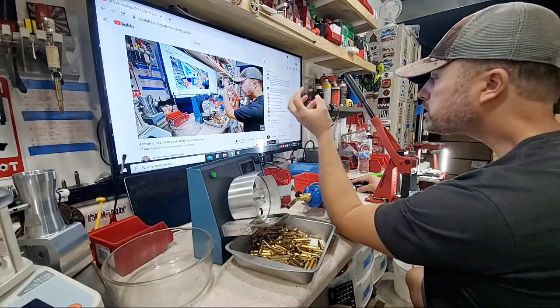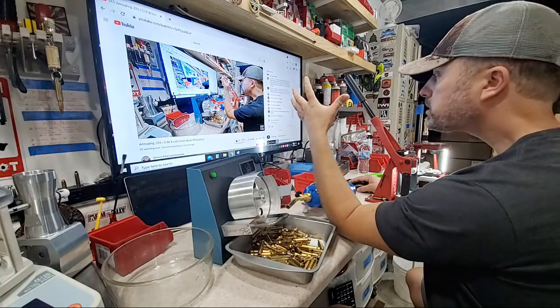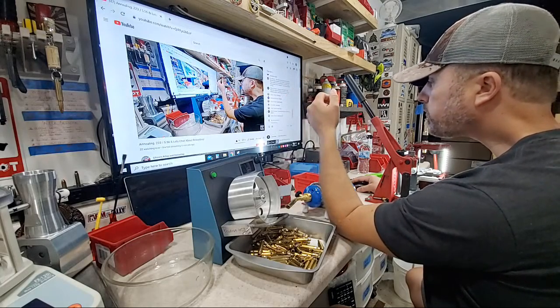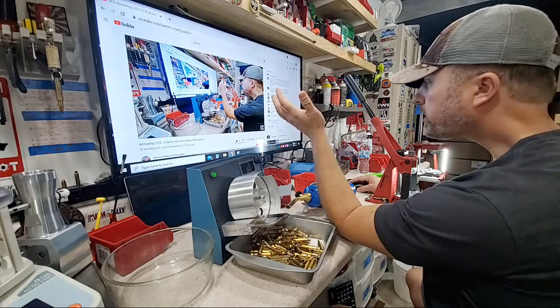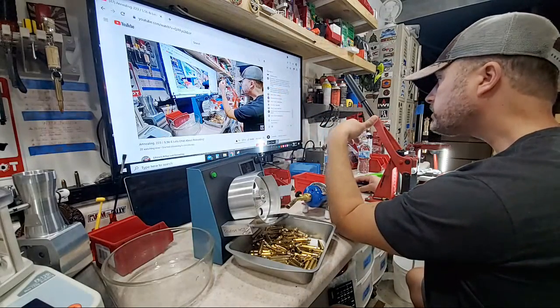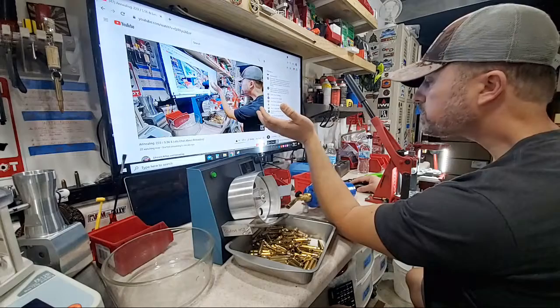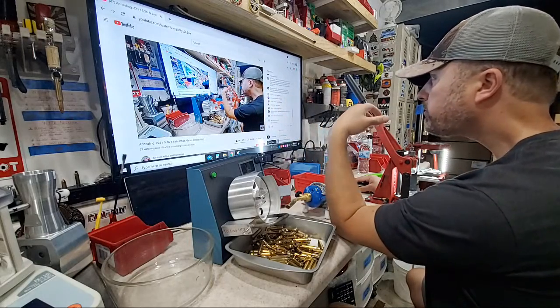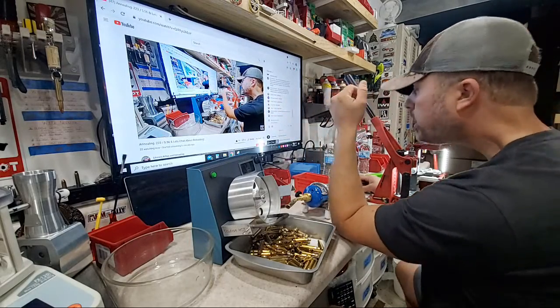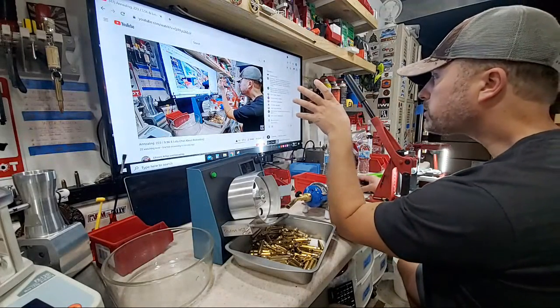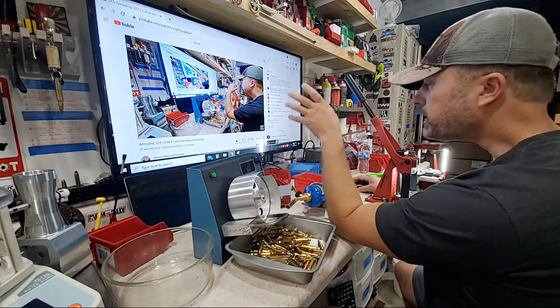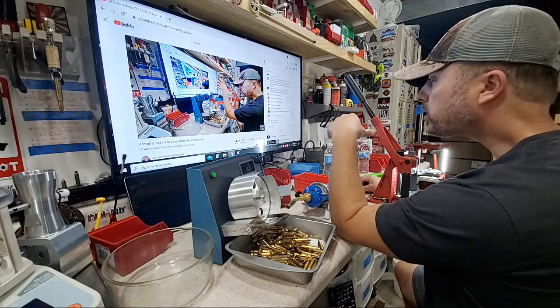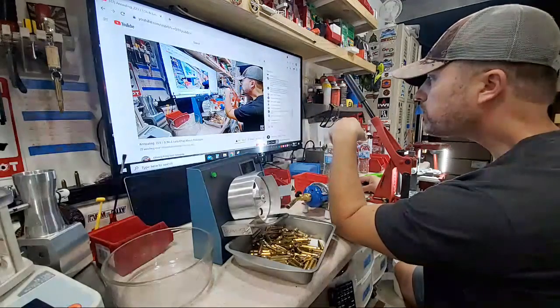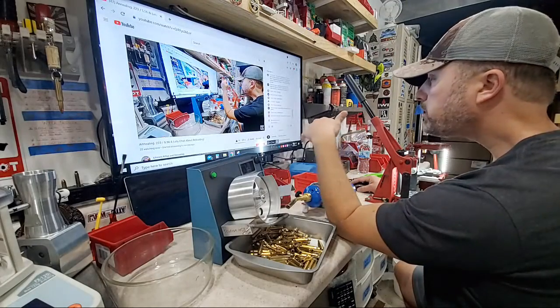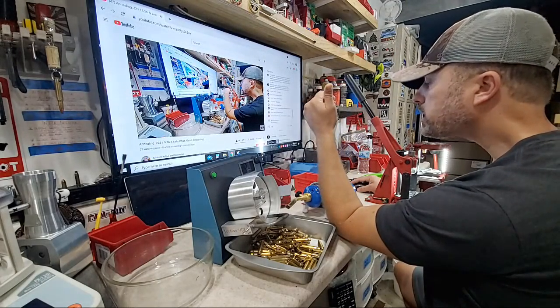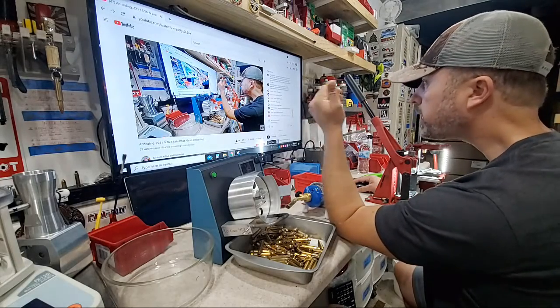What happens is that brass, when you fire it, expands into the chamber. For example, if it's a factory chamber, it could expand 5 thousandths of an inch, and then you bump it back 5 thousandths of an inch with your full length resizing die, and then you refire it, and that's what's called work hardening the brass. What happens is that brass will get brittle. You start getting split necks. For example, in an AR in 5.56, if you're not annealing, you might only get 4 firings out of that brass rather than 6 or 7, for example's sake.